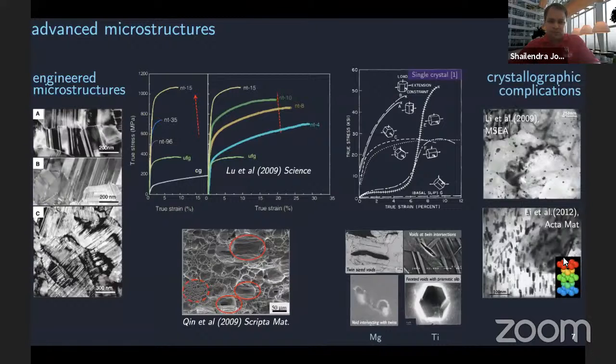In this case, for example, the particular type of crystallography that we are referring to is hexagonal close-packed structure, shown here at the bottom right, which can result in highly complex stress-strain responses that are orientation dependent, plus potentially tension-compression asymmetry, depending upon different mechanisms that can get activated, depending upon how you load the systems. That can have a tremendous effect on how damage evolves.